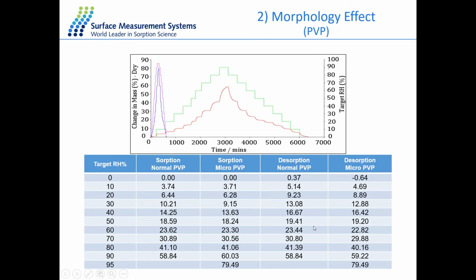And this table summarizes all the equilibrium content at different humidity for the two different samples. These two samples show very good agreement for the equilibrium content during sorption and desorption, and especially in the lower humidity range, the values are almost the same. So the sample size in this case didn't affect the moisture uptake capacity, but will significantly improve the sorption kinetics for the measurement with the smaller amount of sample.